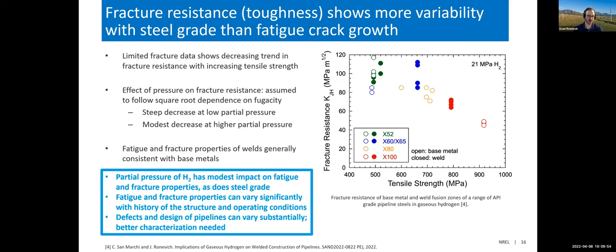We also see that fatigue and fracture properties of welds are generally consistent with base metals. So some overall takeaways here are that while partial pressure of hydrogen and steel grade both have a modest impact on these structural properties, these properties can vary much more significantly with the history and structure of the pipeline and its operating conditions. So, does the pipeline have a lot of defects? Does it have a lot of stress concentrations? Is it operating at high pressure? These defects and design aspects of pipelines are kind of more dictating in a pipeline's ability, at least a steel pipeline's ability to handle hydrogen. But really, we need better characterization of those aspects and of more types of steels used in US transmission pipelines.